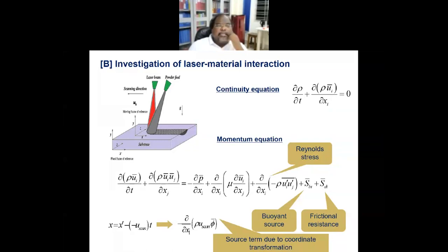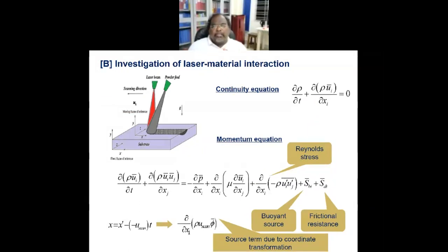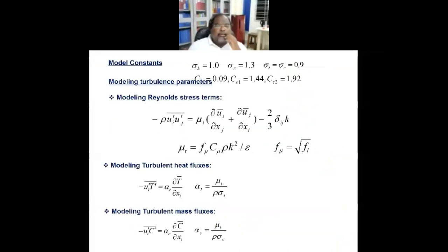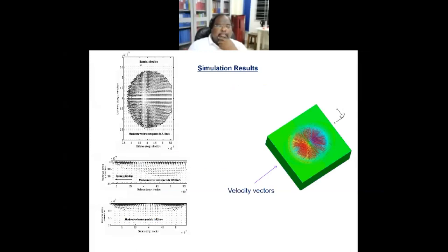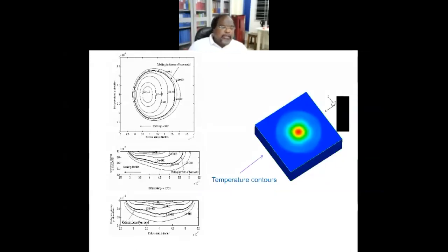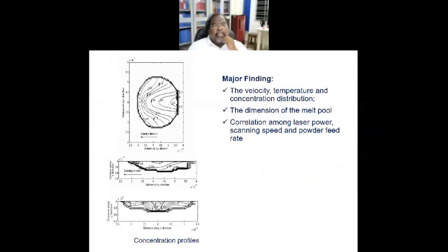Next came the laser material interactions, and from there we tried to get the different parameters of the powder. Here again the same standard formulations were used, nothing special, so I'm not going into details of that. Based on these simulations, we came out with different contours, like the thermal profile. The major findings were the velocity and temperature distribution, and of course the dimension of the melt pool, and the correlation among laser power, scanning speed and feed. These are the major information we got from the simulations. And now we try to use this information for developing the system. That was the basic purpose of this simulation.